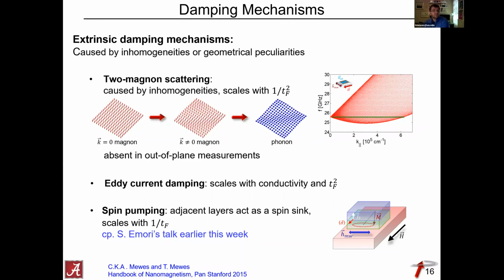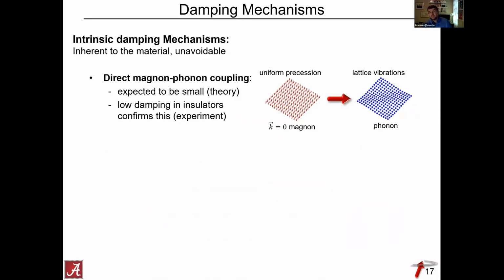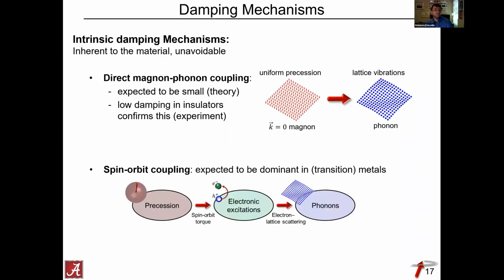Which brings me then to the intrinsic damping mechanisms, which are probably the ones that we're more interested in from a physical point of view, because they are inherent to the material, they are unavoidable to some extent. The first one you might think of is the direct magnon-phonon coupling, which is expected to be small from theory. And I think over the years, with the extremely low damping that we get in insulators, we've seen that this is indeed not the dominant limiting damping mechanism in typical transition metals.